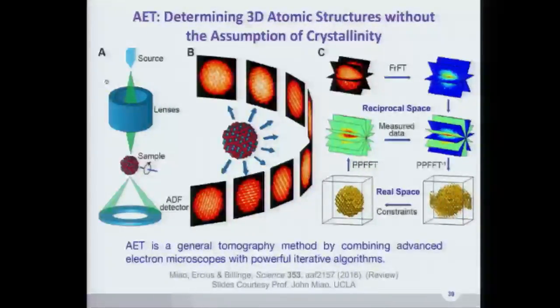They do this kind of atomic tomography, and they now have a scanning version of it. So they can tell you the atomic positions with less than 10 picometer resolution, right? So they really, really precisely know the atomic positions. So what we wanted to say is that if we looked at the atomic positions from theory and experiment, the simplest case you could do is just compare those, right?